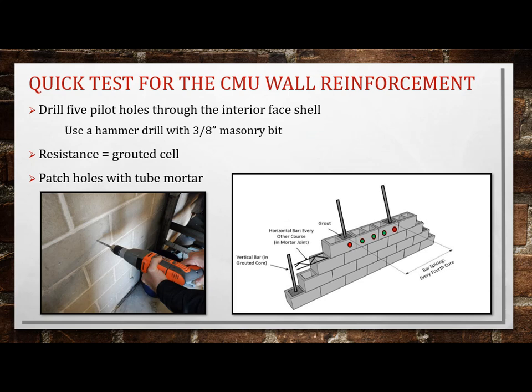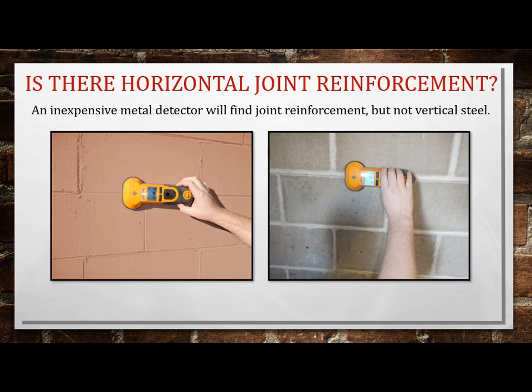So this 5 hole test, you would do on the inside. Don't do it on the outside. Then you patch the holes. You can buy a tube of grout and patch all those up and close it. No one would know you're there. Another inexpensive test is to determine if there is horizontal joint reinforcement. We bought this metal detector at Lowe's for $160, and it will find joint reinforcement, because joint reinforcement is only about 3/8 of an inch from the surface. It's important to know, is it on 16-inch centers, 32-inch centers, 48-inch centers? It's all information that we need to know.